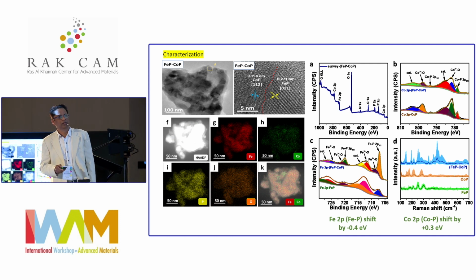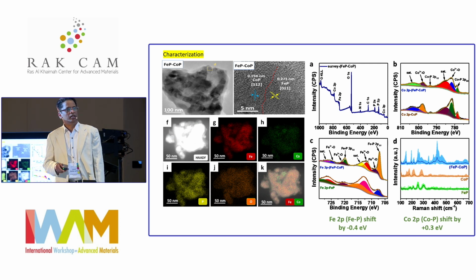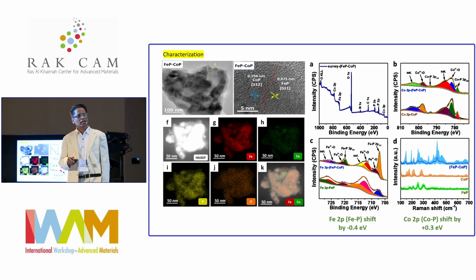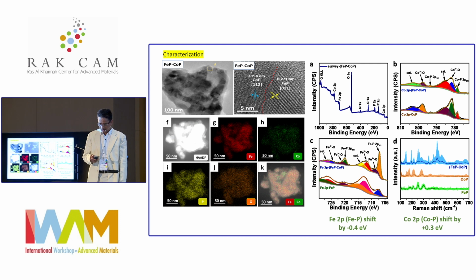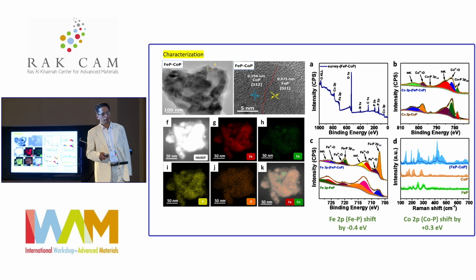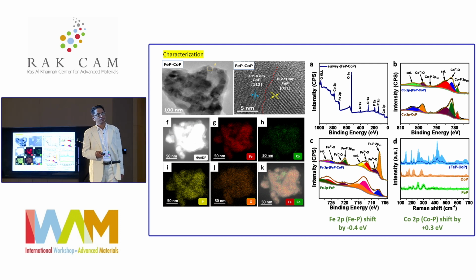And the Raman analysis also shows, in addition to that, the presence of surface oxide, with peaks corresponding to Fe-O and Co-O bonds.